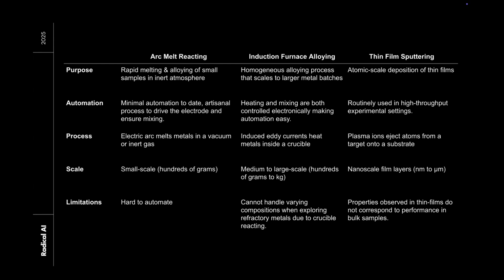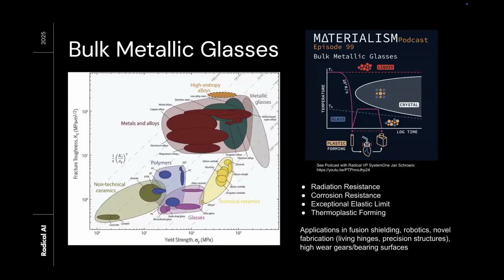So at Radical, we're working on arc melt reacting and automating arc melt reacting. The first test case that we're looking at is bulk metallic glasses. If you look at this Ashby plot of yield strength against fracture toughness, you see that bulk metallic glasses sit in this top quadrant where they have exceptional yield strength and very high fracture toughness compared to conventional ceramics.